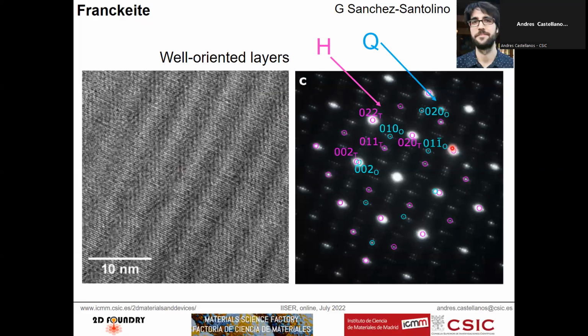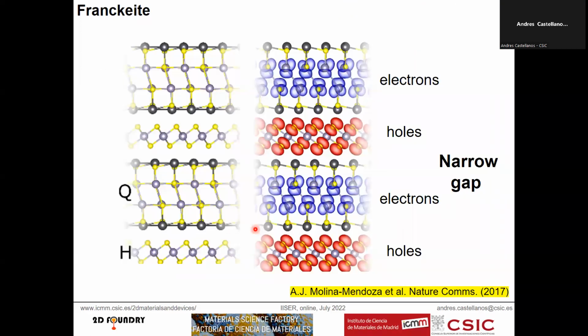And these points here are sharp enough that it is telling you that these are really well-oriented layers. So it's not like they are randomly oriented. They are really stuck in a particular order. And we see this wavy pattern that has been reported already in the TEM studies. And I will come later to this because this is actually not completely well understood. So this is a moire pattern, but it's not a trivial moire.